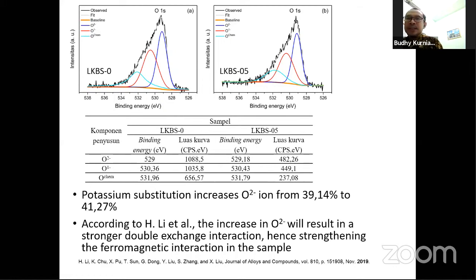In this XPS result, potassium substitution increases the O2- ion, from 39.14% to 41.27%. According to other researchers, an increase in the O2- ion results in a stronger double exchange interaction. If the double exchange interaction becomes stronger, it strengthens the ferromagnetic interaction in the sample. This result will be used to explore the magnetic properties of the sample. Next, please.